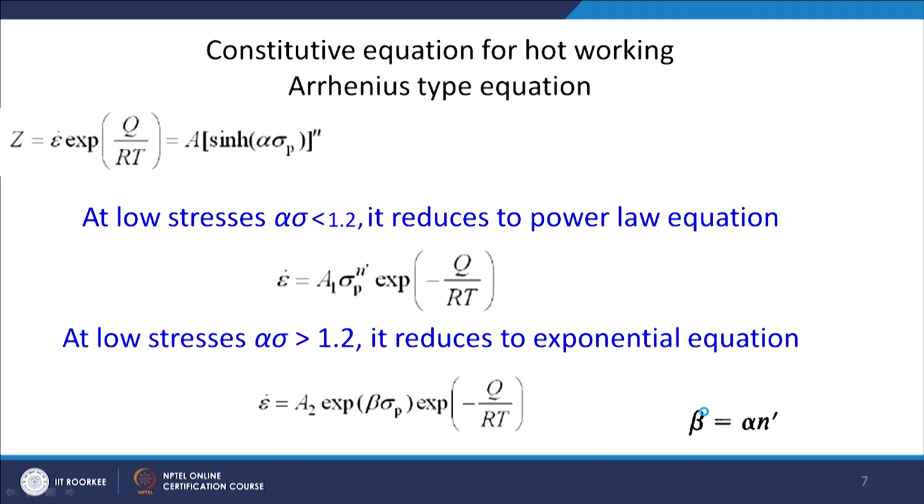Now, this Arrhenius type of equation, this hyperbolic equation, I would call a general equation for a very large window of strain rate. Of course, when you are talking about strain rate, it is ultimately related to stress as well. So, at low stress, this same equation can be reduced to a power law equation.